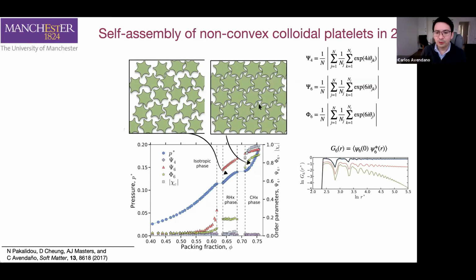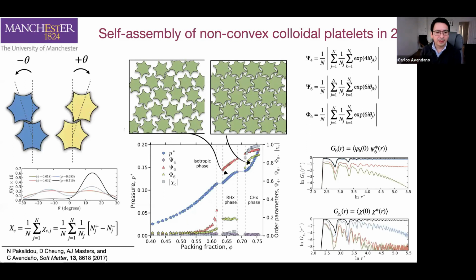That is producing something very interesting. That curvature in the edges of the particles is promoting the formation of a chiral phase, because that shifting between the 2 edges takes place in the same direction all the time. So this is a very nice example of having a system that is not chiral, but promoting the formation of something that has a chiral structure. And again, that arises just by the non-convex shape of the particles.